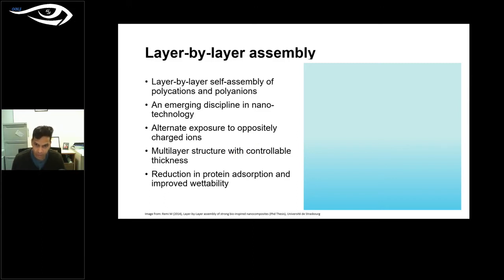And even though, from the sounds of it, you think that it is actually forming layers and layers, in fact what is happening here is the ions are doing interpenetration. That means they're clumped into both anions and cations after several applications of these layers. So the resultant is a more neutral surface, and that kind of surface is good because it will not attract deposition, because one of the reasons for deposition is that it tends to attract oppositely charged tear elements or tear film chemicals, and that's how the deposition happens.